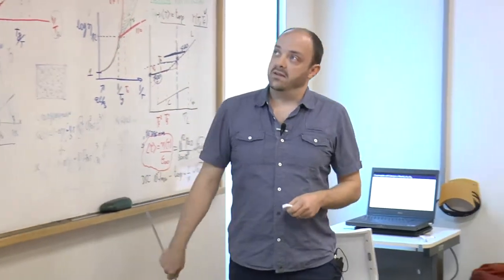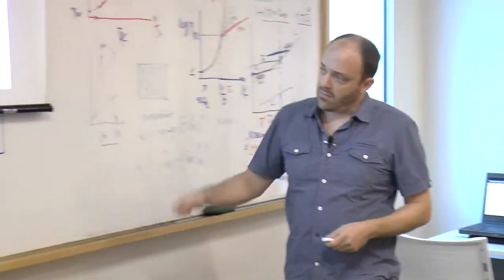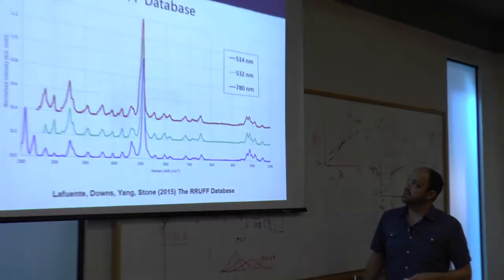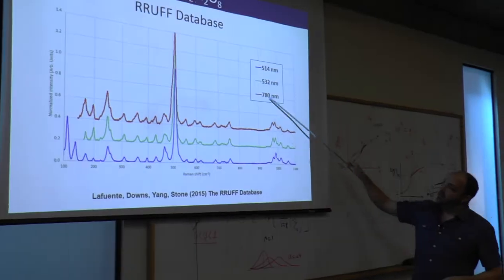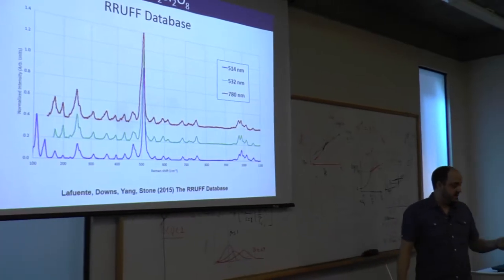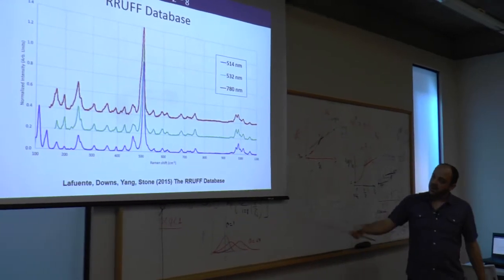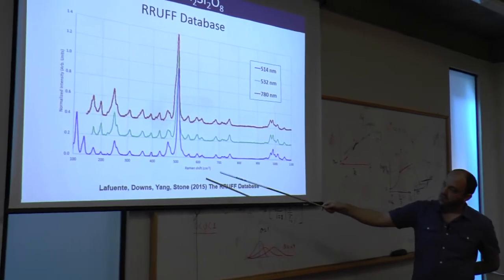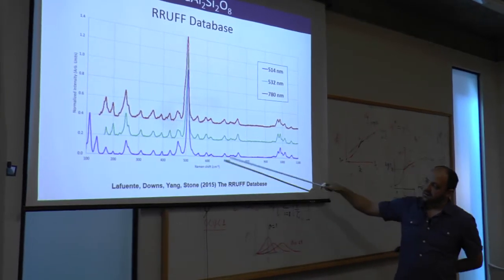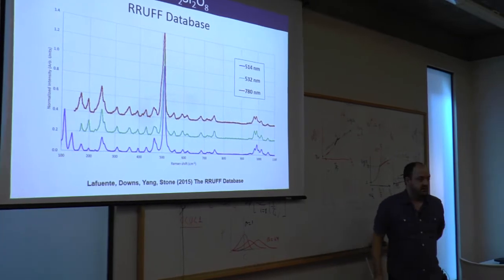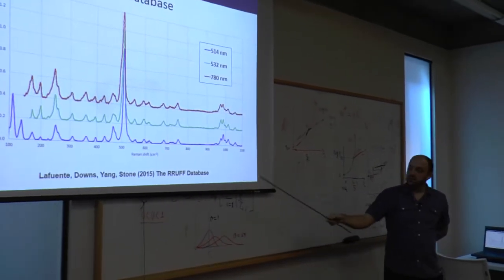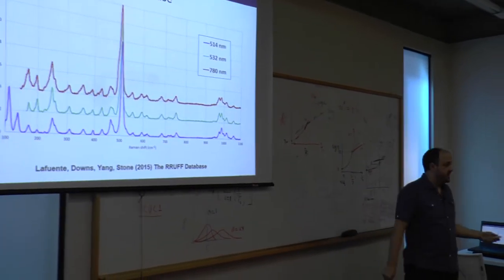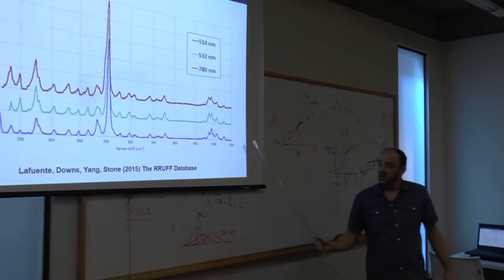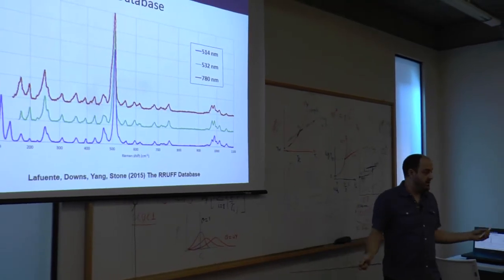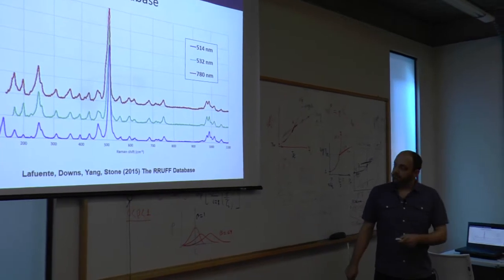And here's an example of that. This is the mineral calcite taken from the database I mentioned earlier. And these are the different wavelengths of the excitation laser. And you can see that pretty much all of the peaks are in identical position in inverse centimeters. So this is why we use inverse centimeters and not absolute wavelength, because it makes the scale the same, no matter what you're using in your initial go.